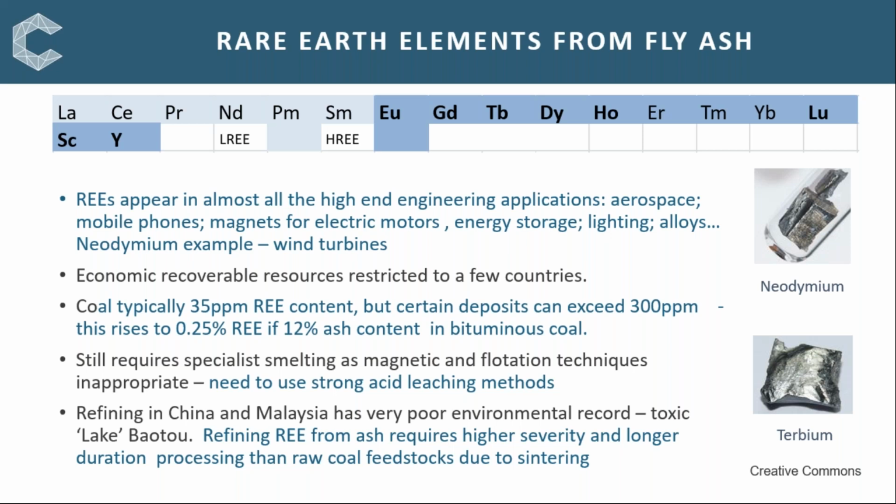The options for improving the extraction are under urgent investigation now. For example, they found that small particles have a higher proportion of rare earth elements. So physical separations are being conducted, and also sonic treatment to open the structure. Expect pilot plants to be operational soon to test these extraction methods and the economics, and of course meet 21st century standards for environmental processing.